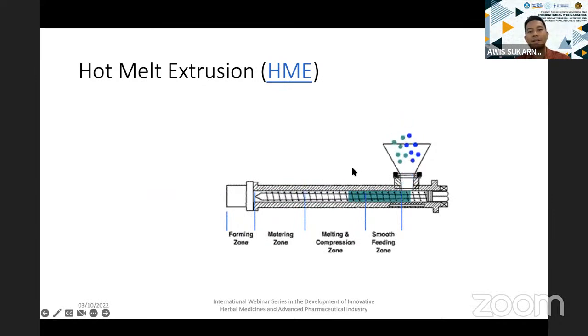Okay, so as in the name of the technique, it is hot melt extrusion. So it means it's hot and melt. So it's going to apply heat to the sample. So let's say some of the active ingredients are very sensitive. For example, let's say you have a plant extract. Some plant extracts are quite sensitive to the heat. So let's say the degradation point of the sample is 100 degrees. So you need to use a polymer that has a low glass transition temperature. For example, polyethylene glycol, the transition temperature is roughly between 40 to 50 degrees. So you can use that. And then you combine it with your API or your active ingredient or your extract, and then you can extrude it without degrading your active ingredient.